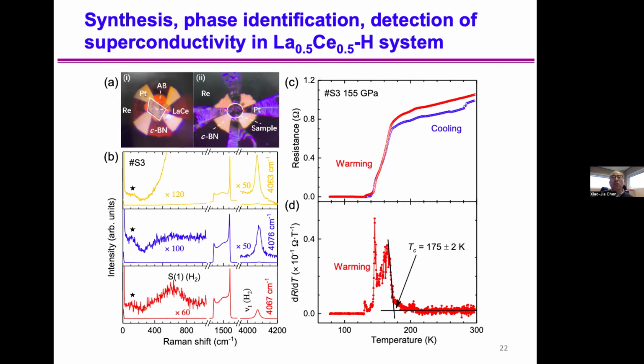Here is the in situ measurement. We put our synthesized diamond cell in a cryostat, a low temperature cryostat. Then we can get Raman and resistivity at the same time. You can see the measurement showing resistivity in a warming run and cooling run. In both runs, resistivity drops significantly, and zero resistivity is already achieved. You can see the onset for this sample is 175 Kelvin.